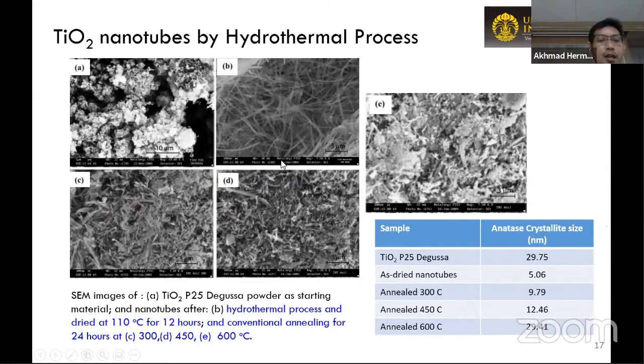initial powder. We can see that there are some small nanoparticles within this big aggregate. That is very normal with nanoparticles, if they are gathered they make this kind of aggregate. But we can still see some small nanoparticles within this aggregate. And B is the sample after the hydrothermal process, dried at 110 degrees Celsius. The B image is the result of the amorphous sodium titanate. So we can see that the nanotube has been successfully formed. But according to the X-ray diffraction result, they are still amorphous sodium titanate. They are not the TiO2 crystalline phase yet.